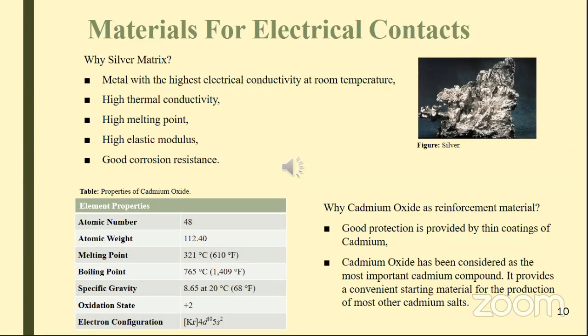And about cadmium oxide, most cadmium produced is electroplated onto steel, iron, copper, brass, and other alloys to protect them from corrosion. Cadmium plating is especially resistant to attack by alkali. Cadmium is physically similar to zinc, but it is denser and softer. The plated cadmium has a smaller grain size than electrozinc coatings, and deposits tend to be more uniform and smooth. Consequently, good protection is afforded by thin coatings of cadmium, and thus, in spite of its high price, it is frequently used for the protection of precision parts.